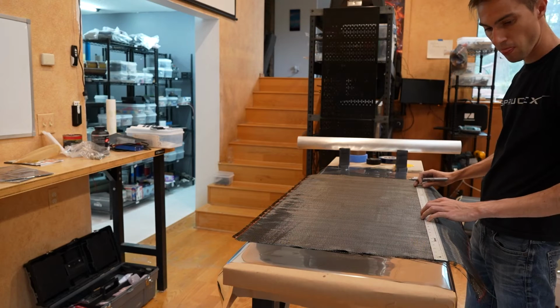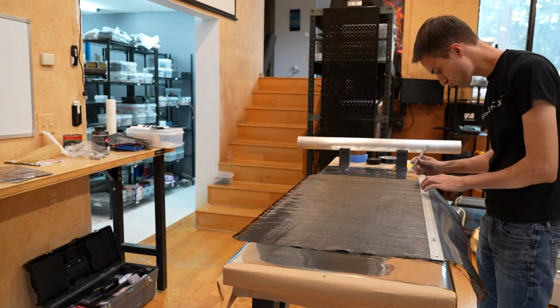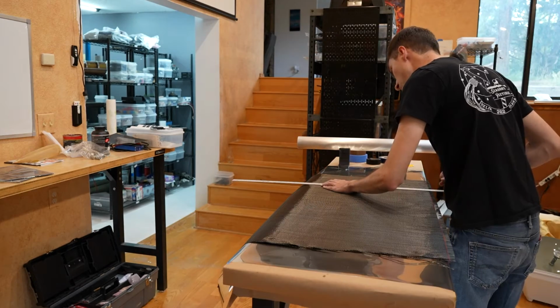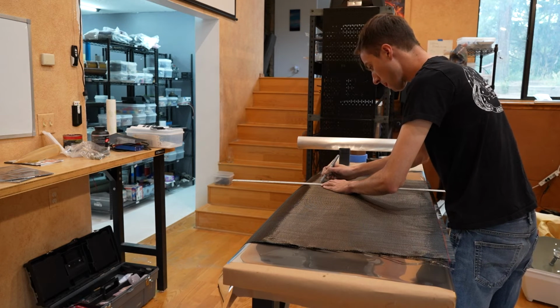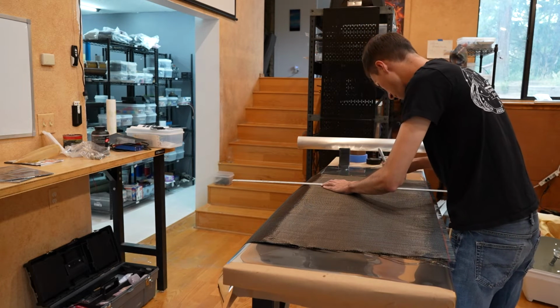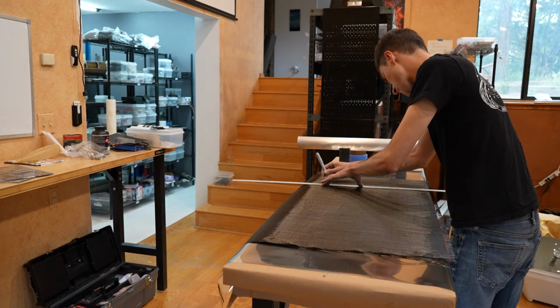The next step is to trim the fabric to shape. Carbon fiber cloth comes in a variety of weaves and weights. For this layup, I used 8-ounce carbon fiber in a standard weave. I wanted my tube to have roughly 50 thousandths of an inch thick walls, so I needed 6 wraps of carbon fiber. To get 6 wraps of carbon fiber, I simply calculated the circumference of the tube, multiplied that by 6, and used that as the length for the section of cloth that I cut out.